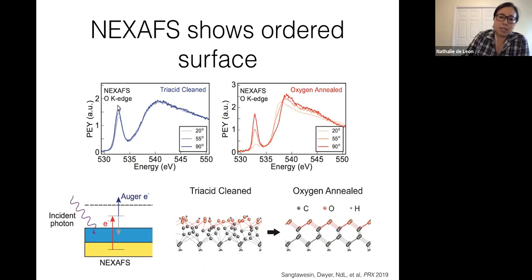And actually what we see is that before and after this oxygen annealing, these NEXAFS spectra are broadly similar. I think a real surface spectroscopist would be really mad at me for saying that, but what I would say is that I see a peak here and then a bump over here, and that's basically the same after you do this oxygen annealing. But the major difference is that after the oxygen annealing, you can see that there's a dramatic polarization dependence.